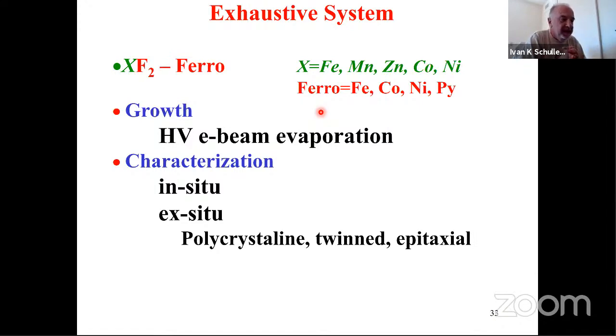By an exhaustive system, I will take a material which is an antiferromagnet, an XF2. I just noticed that I have a mistake here. This should say antiferromagnet. And I put on top of it different kinds of magnetic materials, ferromagnetic, non-ferromagnetic materials, all of them on top of it. I grow all this by high vacuum evaporation, and I characterize them ex situ, in situ. I can make polycrystalline, twin, epitaxial, everything done. So this is a very interesting kind of system. And the ferromagnetic component here can be iron, so the X can be either iron, manganese, zinc, cobalt, nickel. So it's a very exhaustive system, and it has slightly different kinds of magnetic properties, so one can follow the whole thing around.